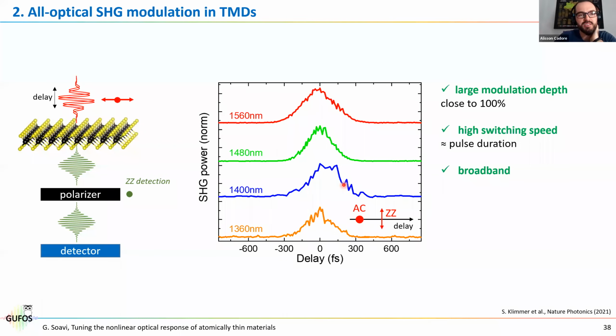No, I was going to ask, what's the limitation for MoTe2 that I didn't get before? It's harder to exfoliate, but this can be solved. But it degrades very quickly in air. Even when we get it CVD, they told us that you can keep it for a maximum of a few hours, then it degrades. Even in the papers from Urbaszek and Xavier Marie, they also say that it degrades very quickly, and it depends a lot on the substrate. So it can be from a few hours to a maximum of 1 month, depending on the substrate.